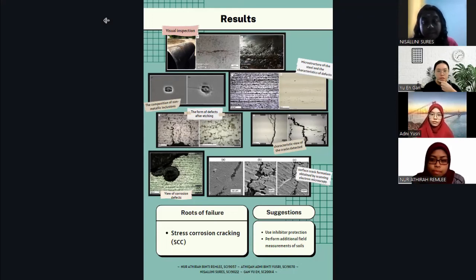From the microstructural observations mentioned above, it can be concluded that the identified cracks in the area of the gas pipeline are related to stress corrosion cracking with the signs of intergranular character of propagation into the depth of the metal, following the mechanism of local anodic dissolution of the metal at the grain boundaries. In order to solve these problems, it is necessary to perform additional field measurements of soils for the investigated section of the gas pipeline to determine the pH, oxygen and sulfide and carbonate ions, as well as the corrosion potential of metal in the soil. Another method of preventing the local anodic dissolution of the metal is the use of inhibitor protection.